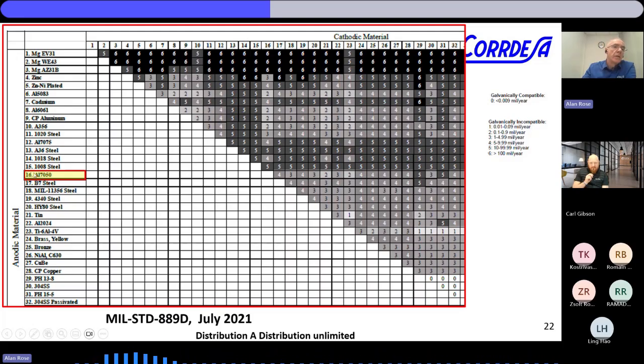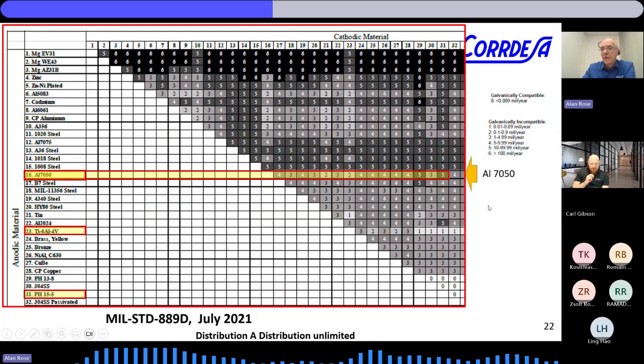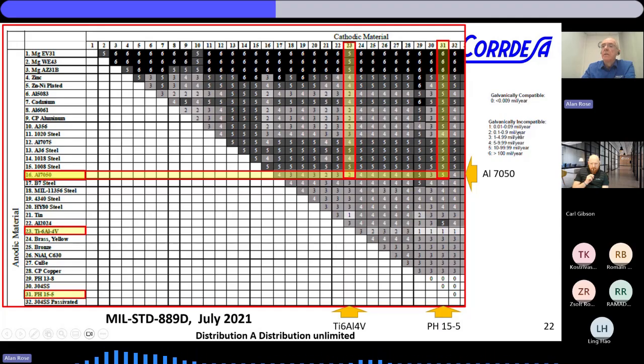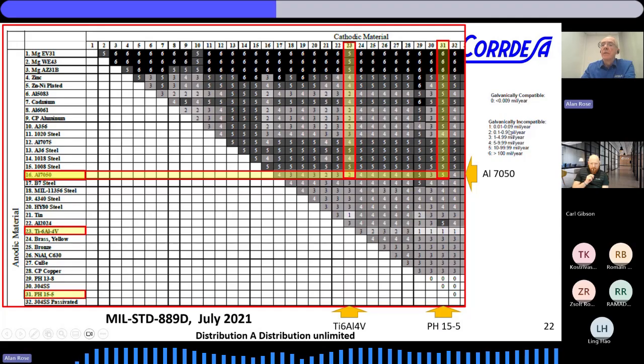What we've got here is all these numbered materials are repeated across the top. So I have aluminum 7050, I've got Ti 64, and I've got PH 15-5. And we just look across here for the 7050, and then we drop down with our expected couple of the Ti 64 and our expected couple of the PH 15-5. And you'll see these categories. Category 2 for the Ti 64, and over on the legend, you've got the mils per year range. This is a linear range. You have to look out for that. So now, this is in line with reality.